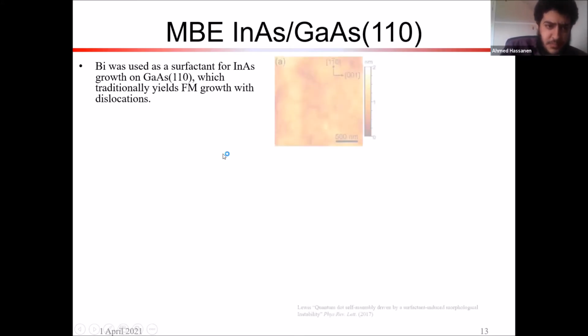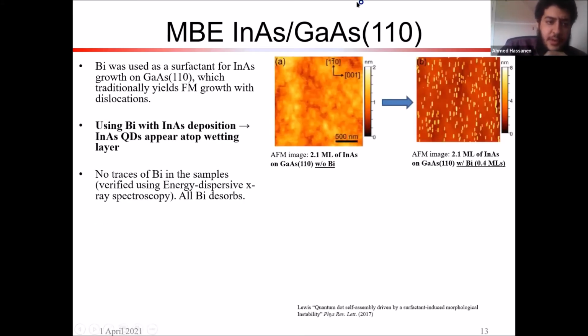As we can see here, this is an AFM image of indium arsenide, relatively smooth, on gallium arsenide 110. But then when we grow with bismuth, simultaneously with the indium arsenide on the 110 gallium arsenide surface, we start to get these quantum dots. You can see up to 8 nanometers high, for example. So bismuth with InAs deposition manages to induce this SK growth mode on the quantum dots.